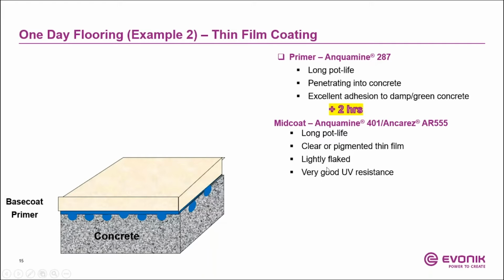The base coat, the example I'm giving, is the Anquamine 401/Ancarez AR555. Again, with water-based, you have long pot life, long time to work with. And you can put a clear down or a pigmented thin film, which can be lightly flaked if you want. With the water-based technology, there is improved UV resistance. So that's another benefit over solvent-free technology, that you get improved UV resistance, okay? And again, these water-based technologies have long working time and also fast cure.